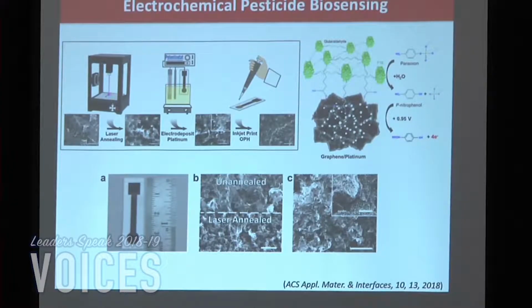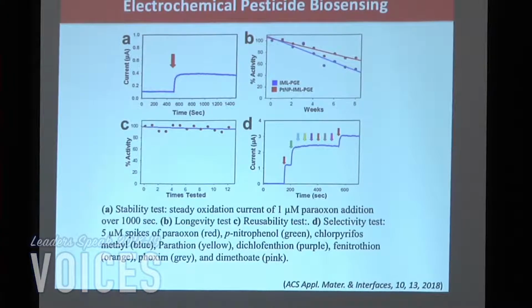And then we tested this pesticide in various solutions. Our results showed pretty good stability. I'll just highlight a few of these results. We showed pretty good activity of the enzyme, retaining almost 80% of its activity after several weeks, with multiple tests. What's nice about enzymes is you can test them over and over again. An enzyme breaks down its substrate, and then it's ready again to bind to a new substrate, so you can reuse those sensors. And then it's highly selective. We tested it against other insecticides and different herbicides in a solution, and they gave minimal interference. So that was a good selectivity test.